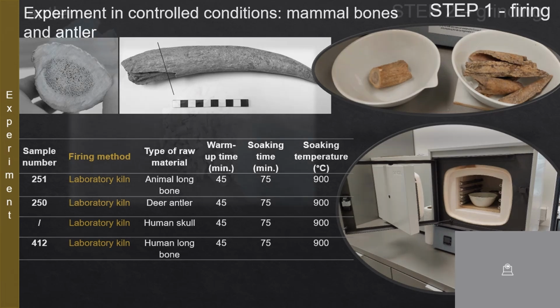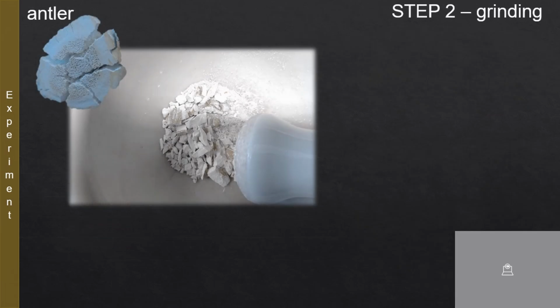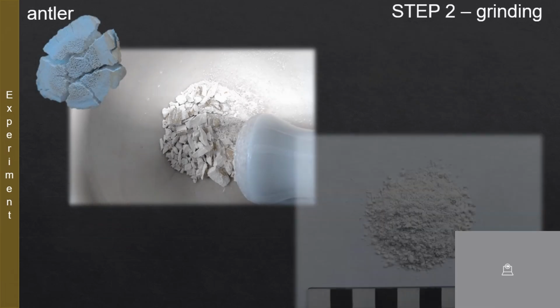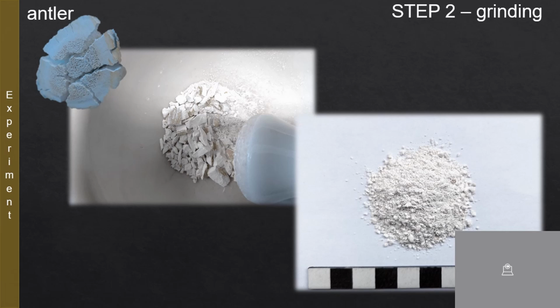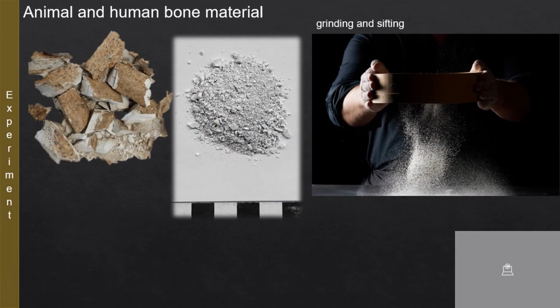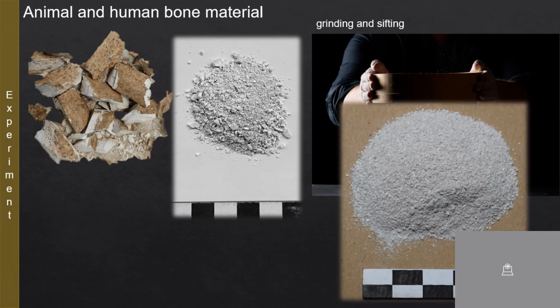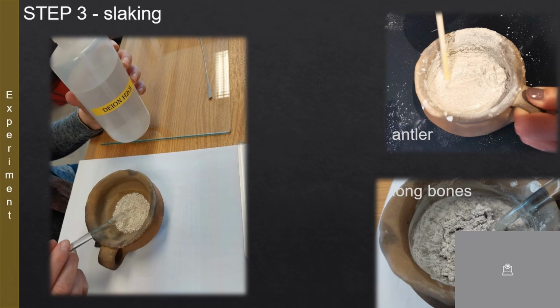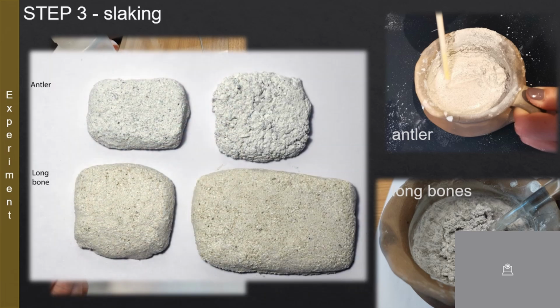After firing in a laboratory kiln, bones were cooled and ground into powder, revealing differences in texture. Therefore, in some cases, sieving was required to obtain a finer powder. Once ground into powder, water was added slowly while mixing to create a homogeneous thick paste, which was then shaped into briquettes to test their strength. After 24 hours of drying, they hardened, demonstrating their potential for bone-based plaster material.